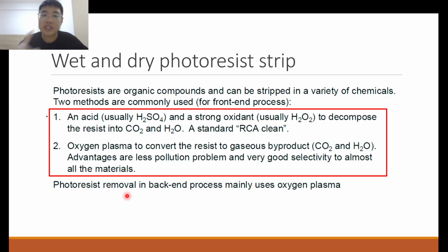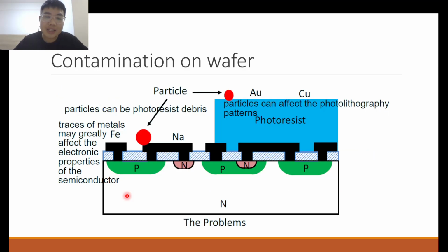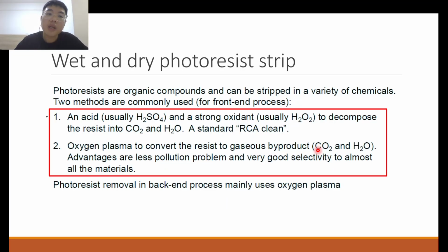So let me first introduce this idea on the wet and also the dry photoresist strip. When you are done with your photoresist, when the photoresist has really served its purpose, we need to remove it. When we remove it, we need to make sure we remove it well, because if not, there would be residue of photoresist, especially in areas like troughs, the vias and all that kind of thing. That would be problematic because your photoresist will remain there and it will be a contamination for any subsequent fabrication steps. So that's why we need methods to strip the photoresist.